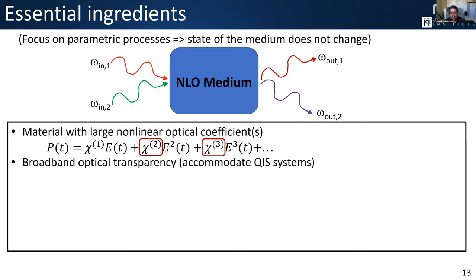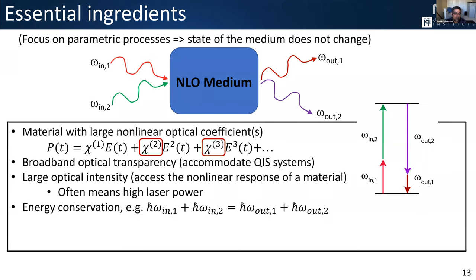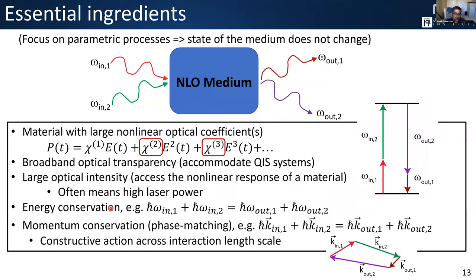Now we need to think about the essential ingredients involved in getting these things to work in practice. We need a material with relatively large nonlinear optical coefficients and broadband optical transparency to accommodate all these different systems at visible and short near-infrared wavelengths. For nonlinear optics, you need large optical intensities to enable the nonlinear response of the medium — with nanophotonics, we can achieve this through resonant enhancement. Then we need to satisfy the core ingredients for parametric nonlinear processes: energy conservation and momentum conservation, or phase matching. Energy conservation you typically take for granted in bulk media and waveguides, as long as you have transparency at those wavelengths.